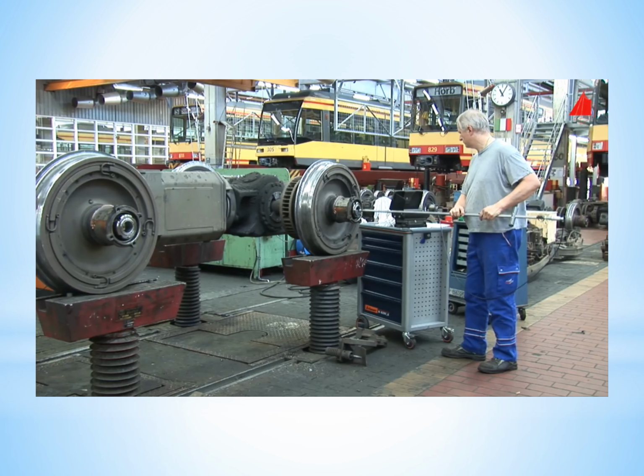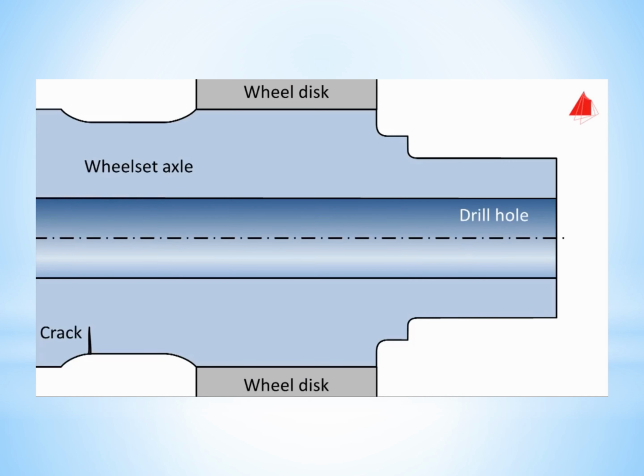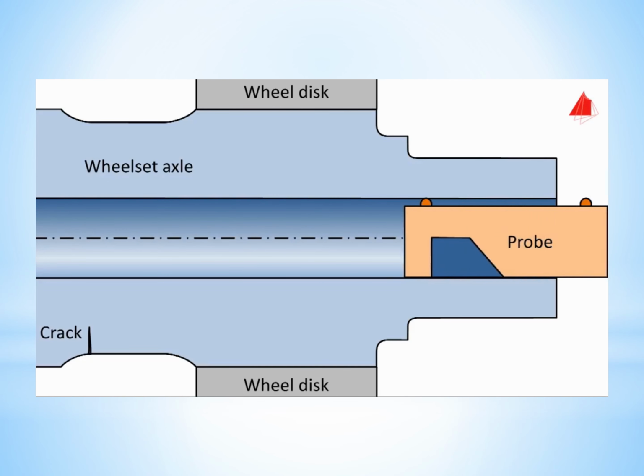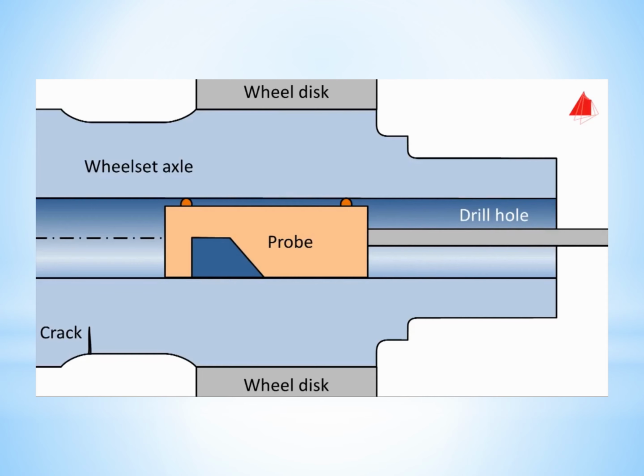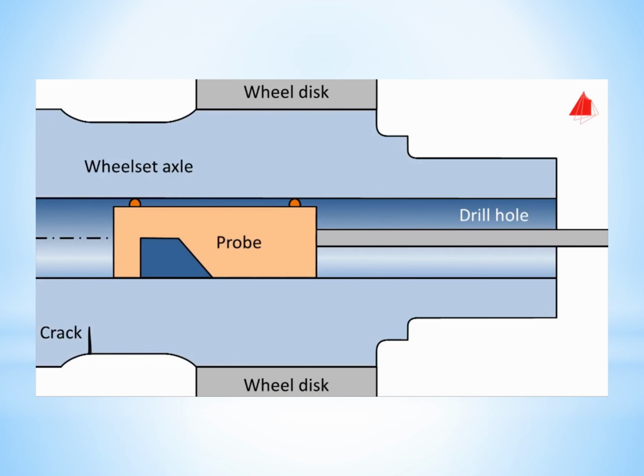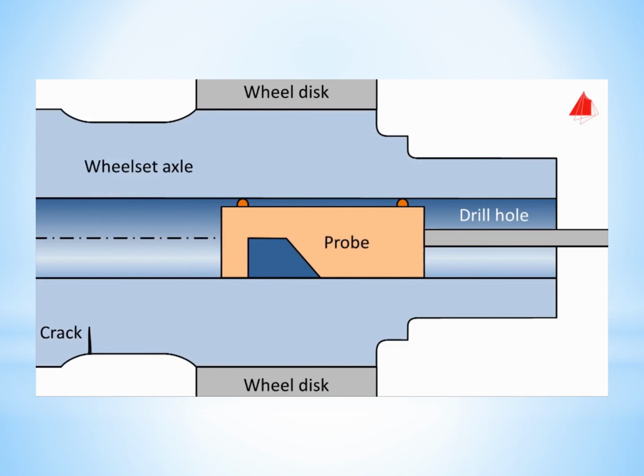monitor closely. The probe has specially been designed for this application. It transmits the ultrasonic pulses at an angle of 45 degrees. At a place without defects, no defect echo returns. But when the pulse encounters a crack which has grown in from the outside, double reflection occurs and a typical defect echo is recorded. It is important to note that also the shape of the wheel set axle may lead to an echo, for example at shoulders.